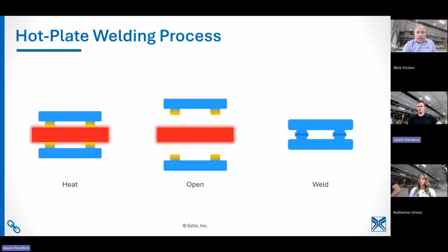It's a really good question with polypropylene. We'd love to get specific to the application maybe after the webinar. I think this is going to be my theme today. Similar to what I said about the PEEK, polypropylene also has a pretty big umbrella. There's natural polypropylene, or there's copolymer polypropylene, and those two react very differently to the heat plate. Some blends of polypropylene require the use of a Teflon coated tool to get that strength requirement. And if you're using just straight polypro, you can get away with those higher temperatures.